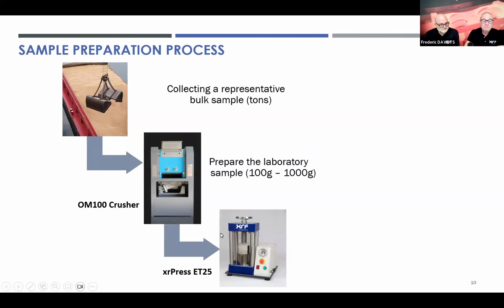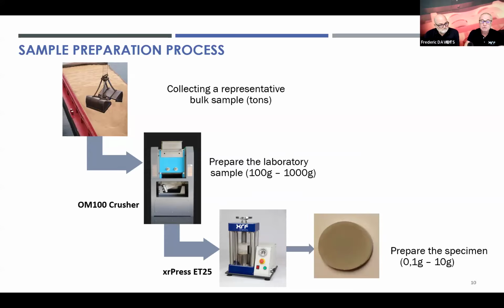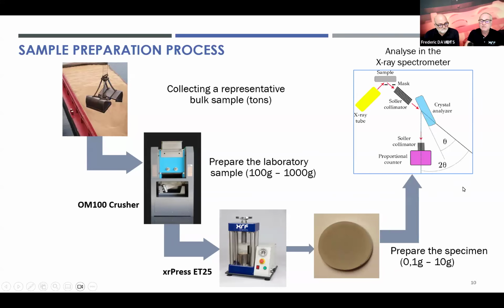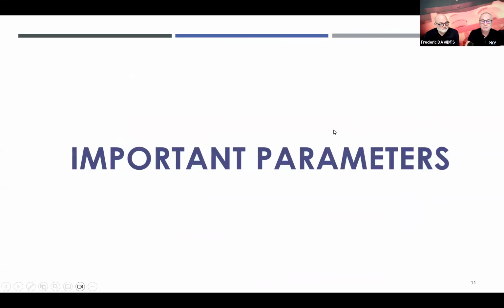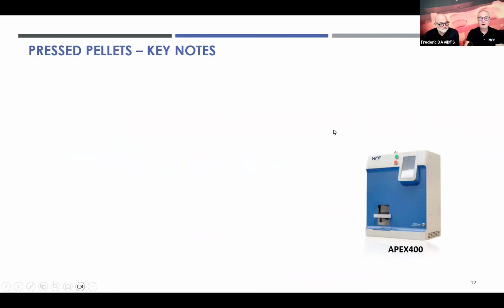Then this sample needs to be prepared into a specimen, and for the pressed pellets method, we will use a press, and we will use many other parameters, as we will see, to obtain the specimen, and the specimen is the sample that goes into our spectrometer. So it is, of course, important that we follow very carefully the procedures, the processes of obtaining a very representative sample from this initial bulk sample. Now, some important parameters